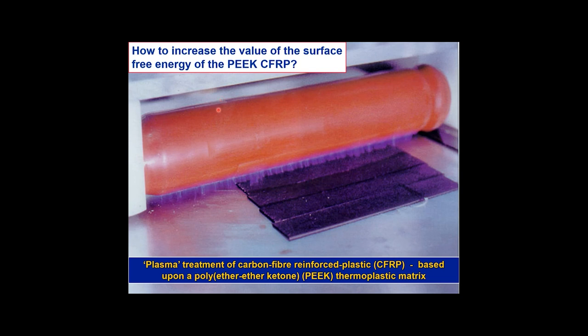The technique we developed is called corona treatment. It's an air plasma treatment. What we have here is an aluminium plate, and here's an insulating, rubber covered roller. If we put a high voltage between the two, we get a spark discharge, and we generate lots of ozone and oxygen radicals. Now, if we pass the PEEK CFRP material, these black strips of carbon fiber reinforced plastic using PEEK as the thermoplastic matrix, under the discharge, the oxygen and ozone radicals in the spark discharge chemically treat the surface. As you might guess, we put polar groups, oxygen groups, onto the surface of this material.